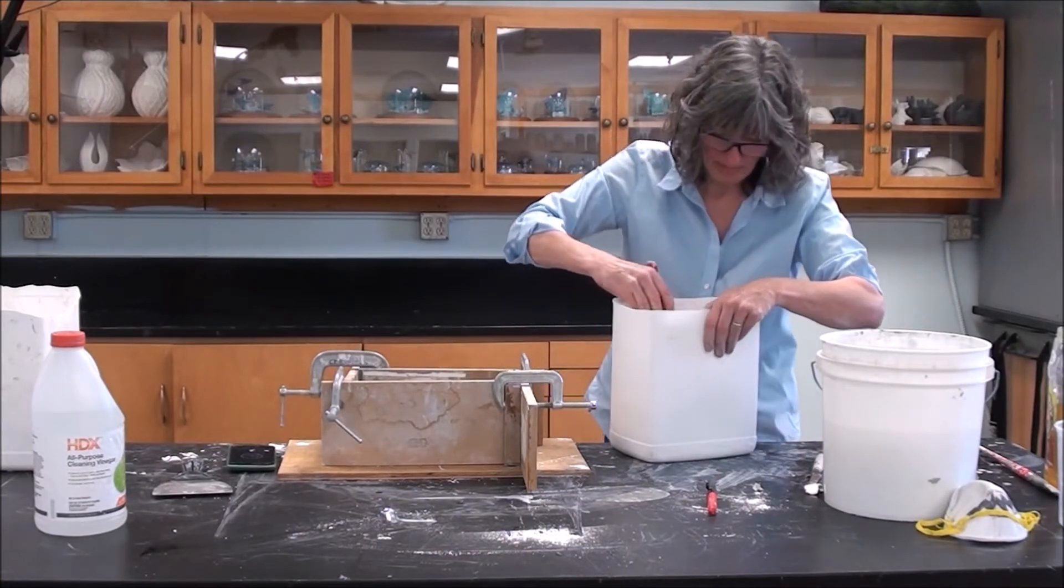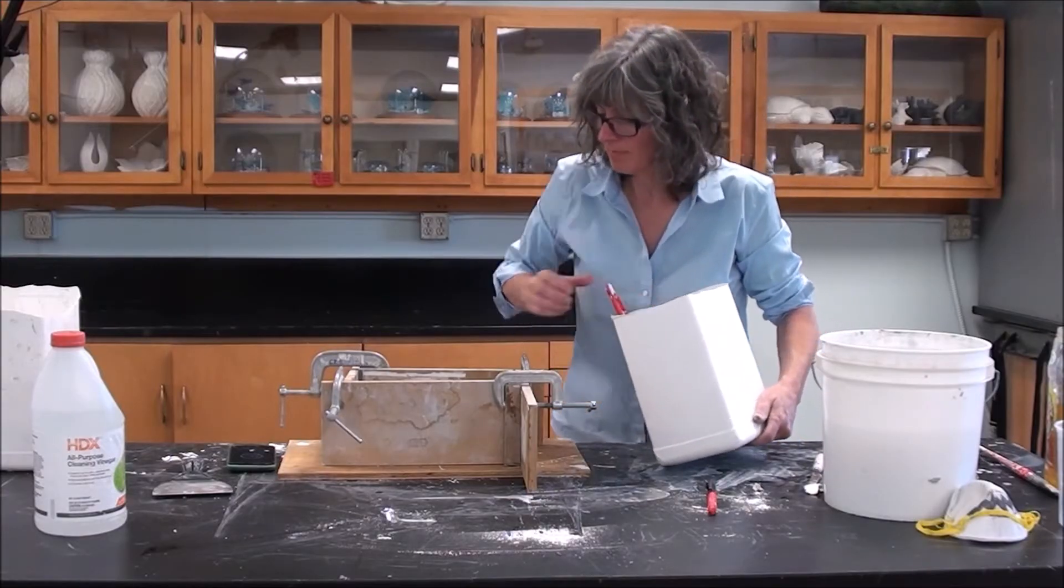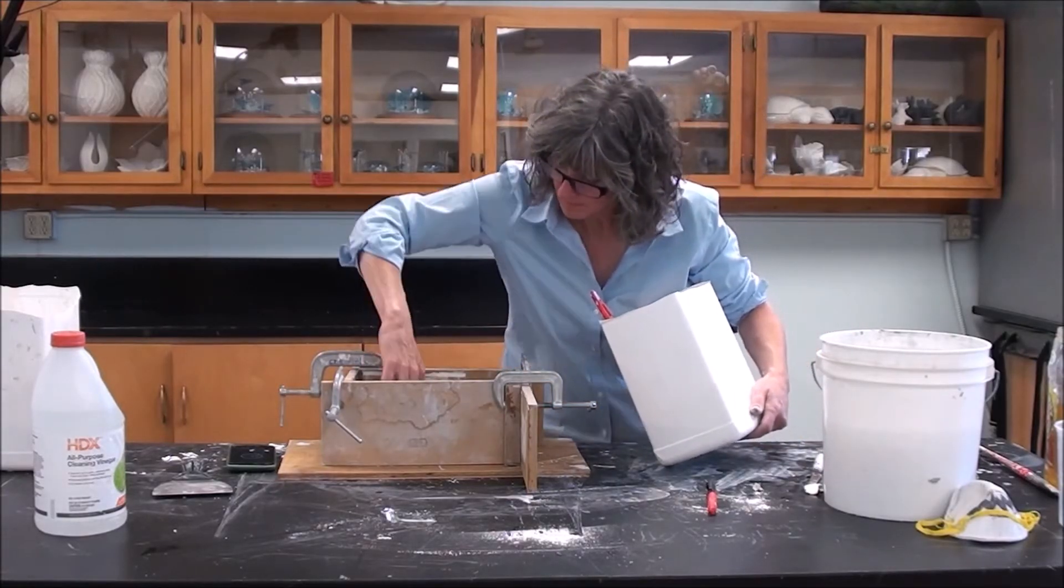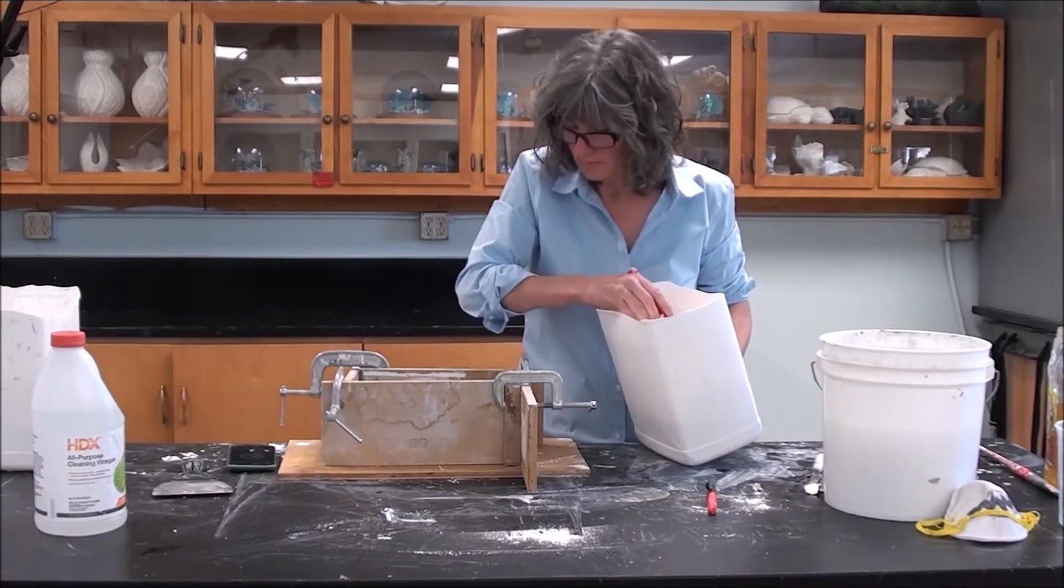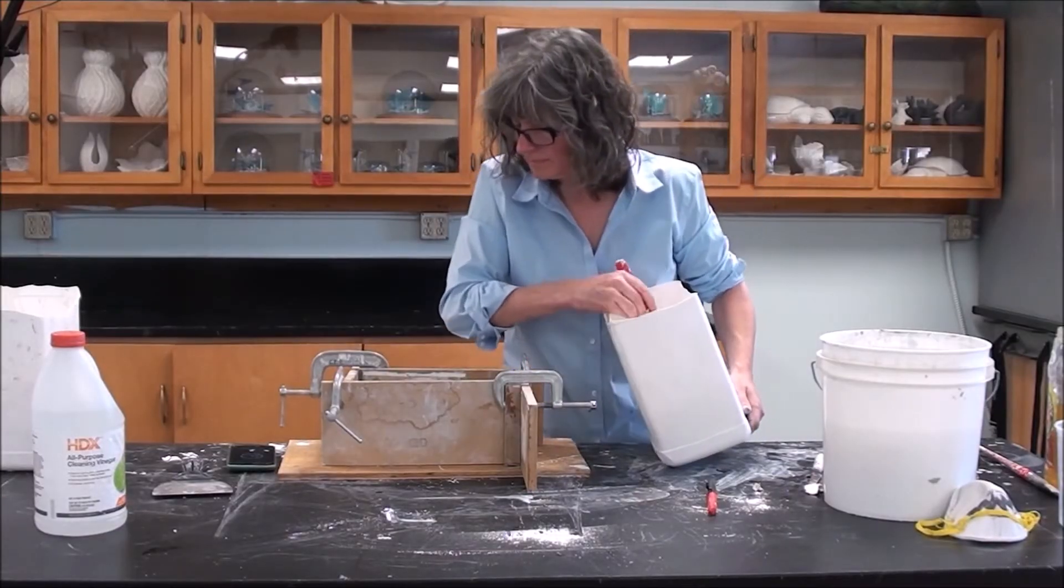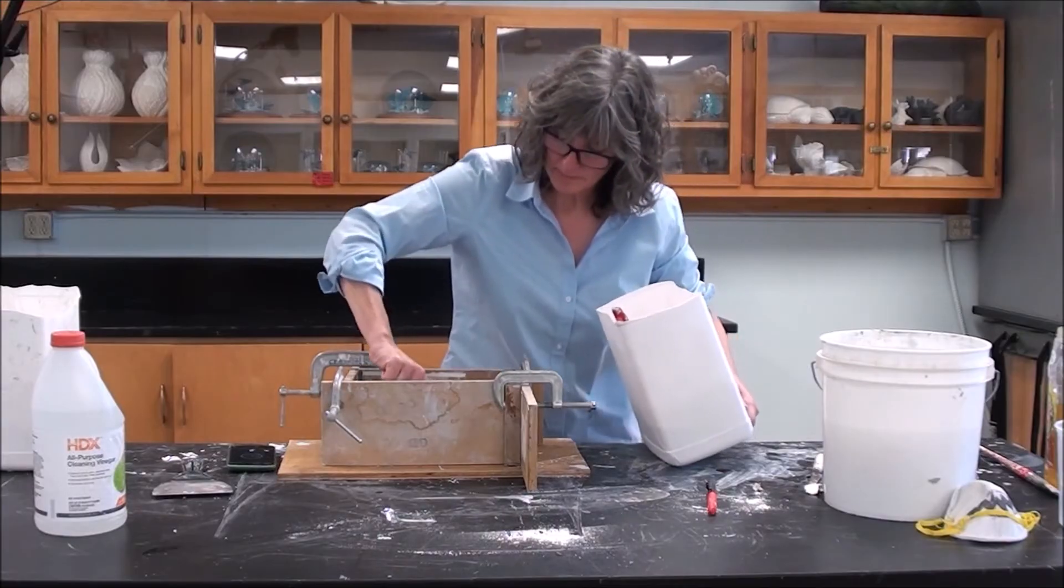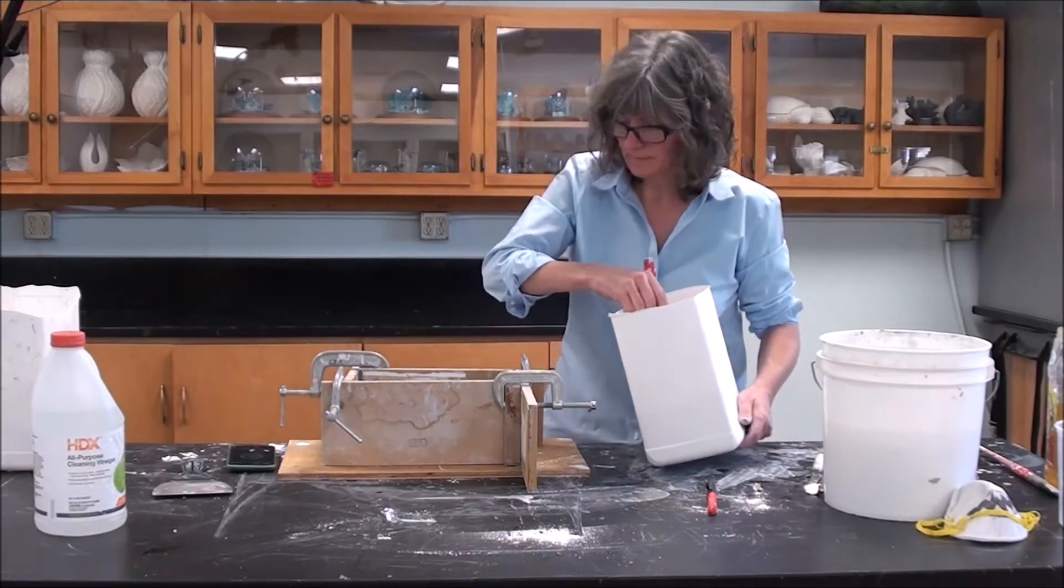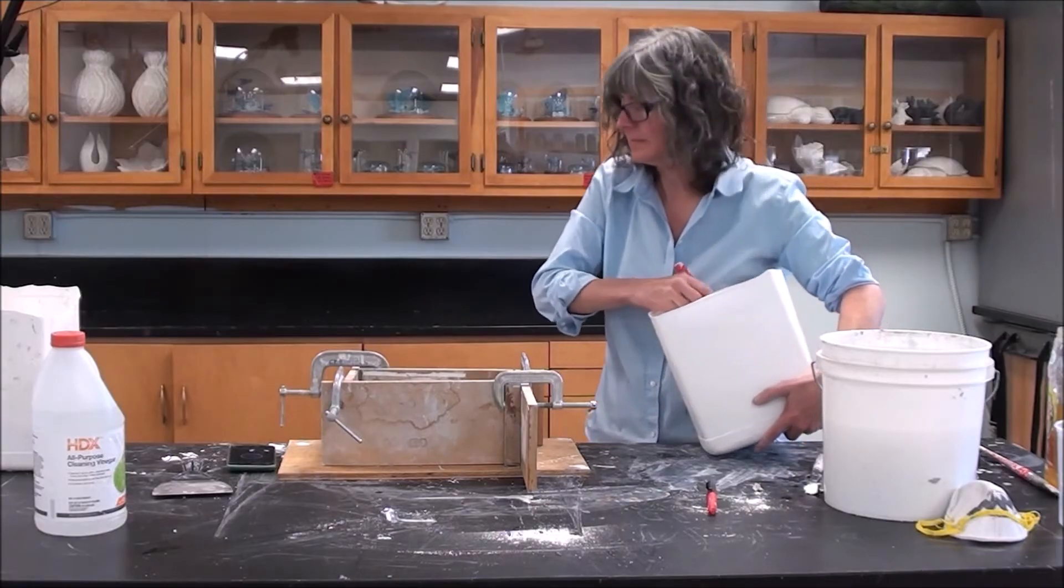There are ways you can speed up your plaster set time. Mixing up your plaster with warm water rather than cold water will speed up the process, meaning your plaster will set up more quickly. If you want to speed up your process, you certainly can use the warm water. I have in the past used warm water and it seems to speed up my process too quickly and I end up creating a sloppy mold. So, I personally prefer to use cold water.